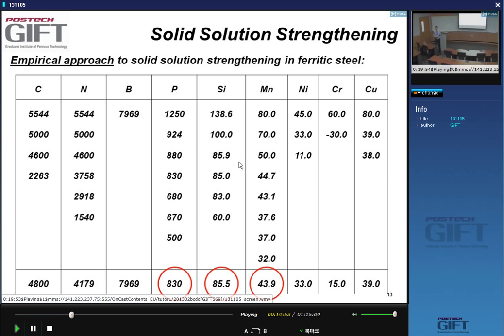very often they do this on steels. And so the concentration of the elements is never measured perfectly. In the sense that, for instance, in the case of this carbon here, are we sure that the person who did the measurements checked that there was no carbon present as cementite or a transition carbide? How sure are we that the carbon was not segregated, for instance, to grain boundaries? We don't know this information, but it's very important, of course.